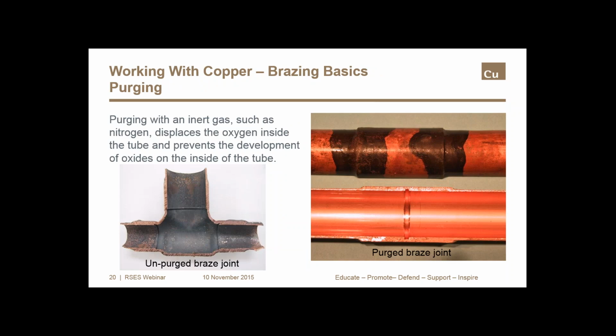It's highly recommended for air conditioning and refrigeration installations that the tube be purged with an inert gas during the brazing process. Nitrogen is typically used as the purge gas, and it displaces oxygen from the interior of the system while it's being subjected to the high temperatures of brazing. This eliminates the possibility of forming oxides on the inside surface of the tube. It certainly makes a noticeable difference, as we can see in the cross sections on the slide.